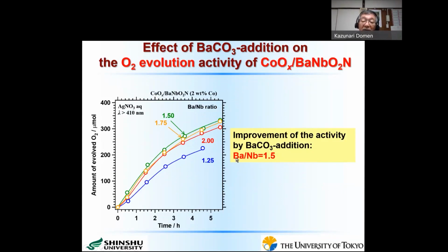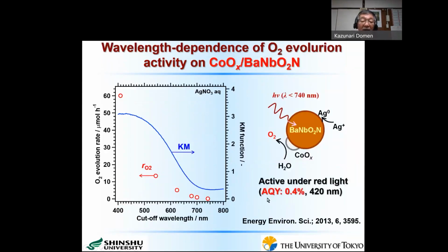So the barium to niobium ratio of 1.5 is the optimum ratio. And we also examined the activity of these materials. I would like to emphasize that the apparent quantum yield of this O2 evolution photocatalyst is at this stage about 0.4%. It is not really so high.